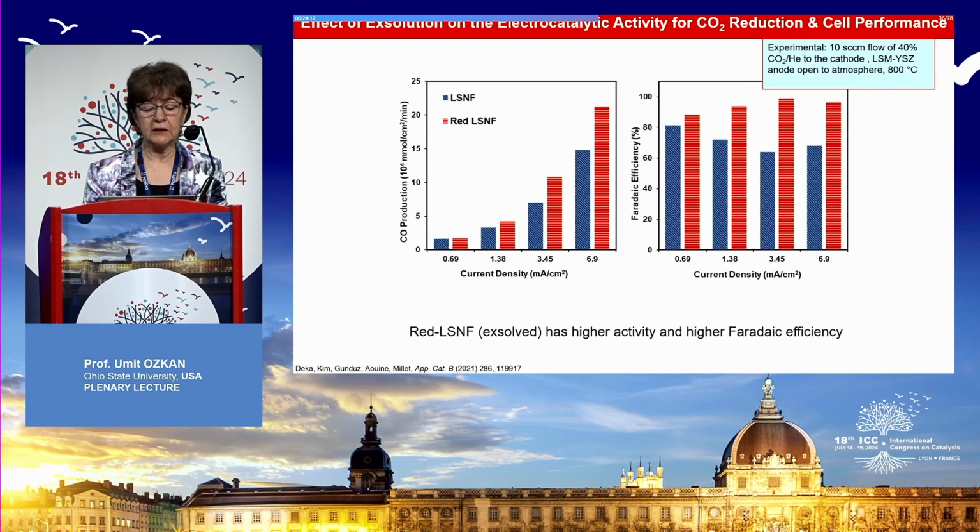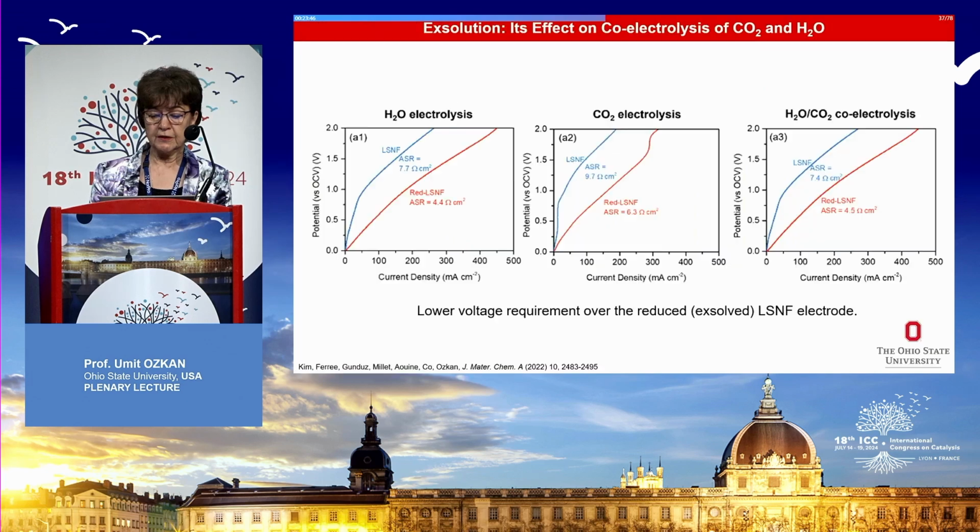If we look at the electrocatalytic activity for CO2 reduction, CO production rate is much higher for the exsolved sample. And also Faraday efficiency is much higher. It is really right around 100% for the exsolved particle samples. So exsolution is improving the catalytic activity and Faraday efficiency.